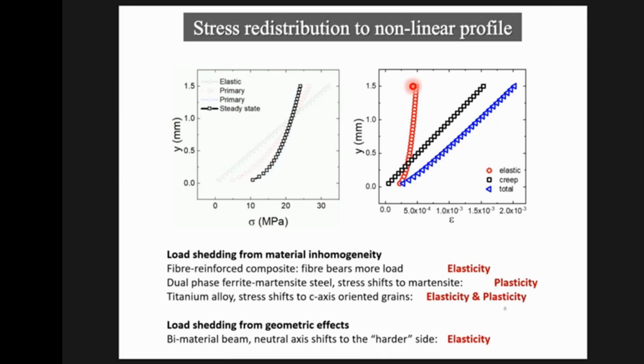And we see this in a fiber reinforced composite. The load is shed from the softer material to the harder material. In a dual phase ferritic martensitic steel, the stress shifts to the martensite, and so on and so forth. This is a case where you have load shedding from a purely geometric effect. Actually, we know this in bimaterial beams. If one half is stiffer than the other, then it'll take more of the load, and therefore the neutral axis will shift to the harder side.